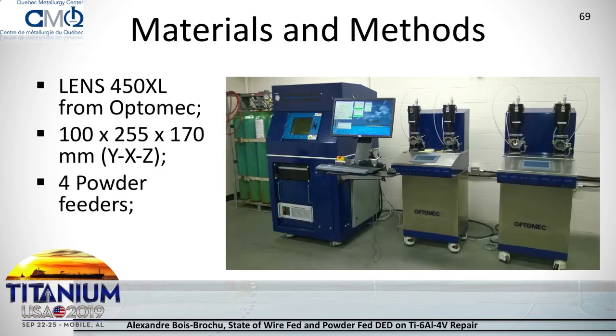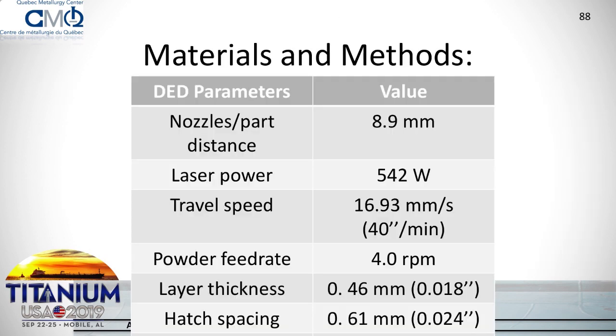So for the powder-fed DED section, we used a LENS from Optomec, the 450 XL, which is their small model. It's all under inert argon atmosphere. And we used a laser input of 600 watts, which is an actual laser output of 542 watts, at a travel speed of 40 inches per minute. And the layer thickness is quite small, with 18 thousandths of an inch per layer, which results in higher precision when building the part, but lower rate of deposition, as we'll see with CMT later on.